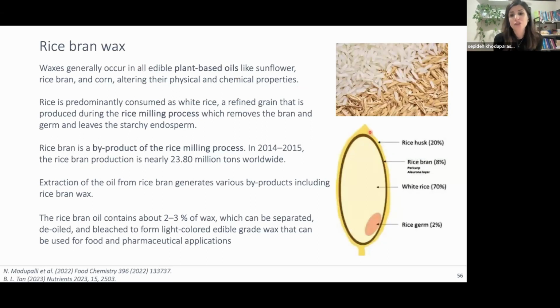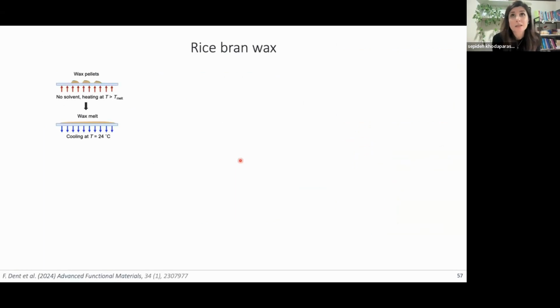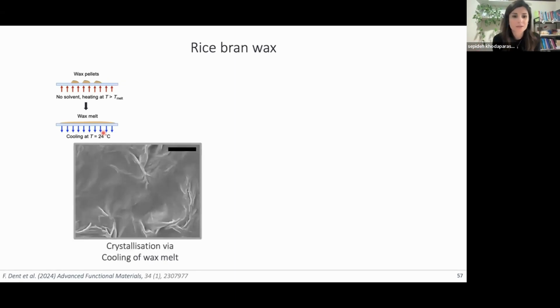We use rice bran wax, which comes from the bran around the rice. It's a small quantity: the rice bran itself constitutes around 8% of the grain of rice in weight, and 2 to 3% of this rice bran is actually wax. But we use loads of white rice, and the rice that we grow looks like this one at the bottom right. The rice that we use is at the top left. So there's lots of material that goes to waste. Rice bran wax is starting to find some usage in different applications, but it's going to waste otherwise. These waxes are typically solid at room temperature. So if you want to make a coating, you need to melt it and create a coating out of a liquid and then wait for it to solidify.